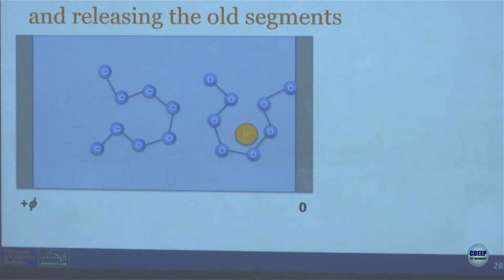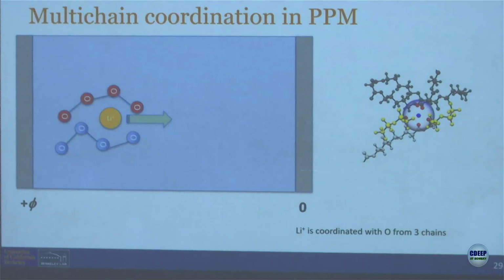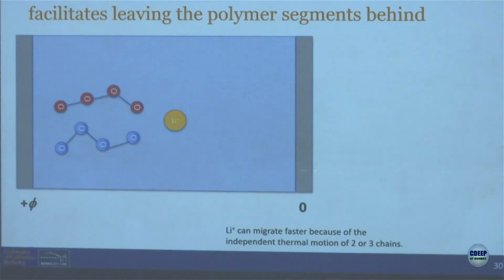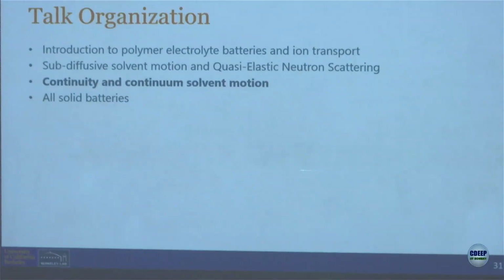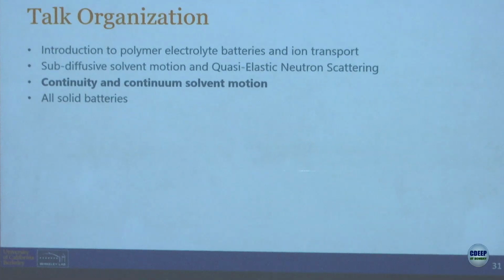And we can see that in our simulations, and I'm drawing this picture because it just makes life a little easier. On the other hand, if you have more than one chain, then the two chains are independent, and it drags a lot less solvent. And that is our hypothesis for why PPM is better than PEO. It's better because the neutral molecule is moving less. It's a hypothesis.